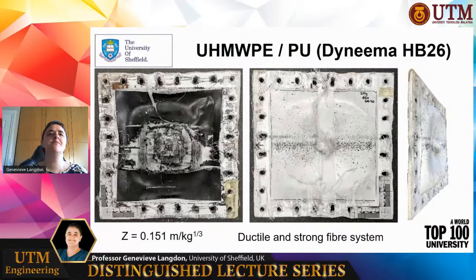This is just a material I'd like to flag as one I believe is one for the future. A lot of work has been done over the years on glass and carbon, but this is ultra-high molecular weight polyethylene inside a polyurethane matrix. It's known as Dyneema. It's really interesting because it's very strong and it's very tough. This is a test we did at 30 grams at 50 millimeters away. You can see all sorts of interesting failure modes in this panel.